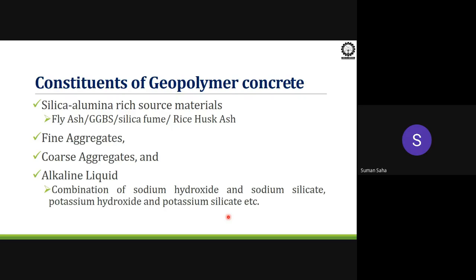So what are the constituents of geopolymer concrete? Firstly, the source material is very important: silica-alumina rich source material. I have given a few examples of those. Then fine aggregate, coarse aggregate, and alkaline liquid. This is a very important part of geopolymer concrete. Usually, in the literature, most present-day work uses a combination of sodium hydroxide and sodium silicate, just because it's easily available and less costly. You can use potassium hydroxide and potassium silicate also, or any hydroxide-silicate solution.